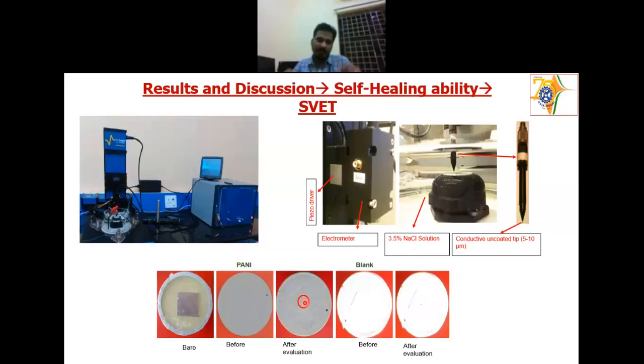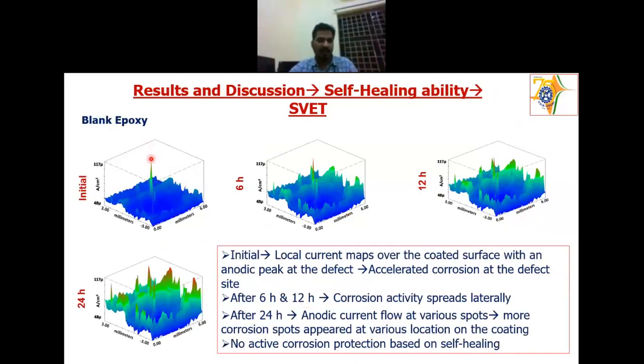So we are making corrosion happen there and seeing whether the coating can stop the corrosion after some time. This is a blank coating, which means we don't have any type of inhibitors here. There is no Pani here. So I made a defect here. You can find that from the defect I'm getting a peak. So this is the anodic activity.